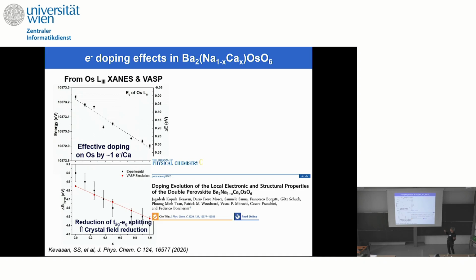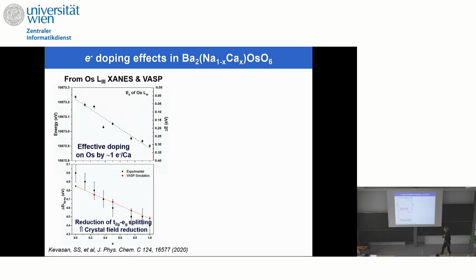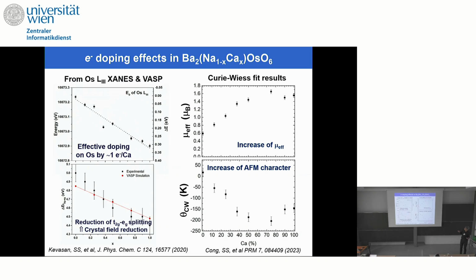We did some experiments, and we also checked that there was a reduction, as expected, of the T2g-eg splitting due to the crystal field reduction in this material. So this is an effective charge doping in the system. We also checked that the effective magnetic moment in the paramagnetic state changes from 0.6 to about 1.6 Bohr magneton for the two end members. It's a monotonic increase, but it's not linear. You can see a sort of saturation around 50% of calcium.